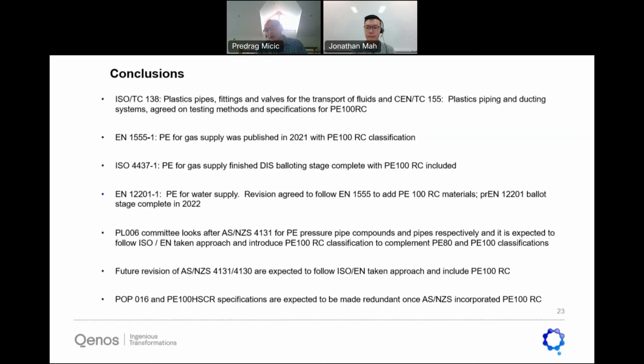That is a difference in terminology, and there's a difference in testing methods now that will be present in the standard versus what is already in POP 16. So in POP 16, we do have accelerated methods that were developed in the past, but we still have the requirements there, etc. But if you look into the specifications, the number of cycles somebody needs to do, or the time it lasts, you have in POP 16 still the notch pipe test, which is required to go for 5,000 hours. Now in the standards, you have the notch pipe test accelerated version, which is 300 hours. So we do not have the accelerated version of that in POP 16.